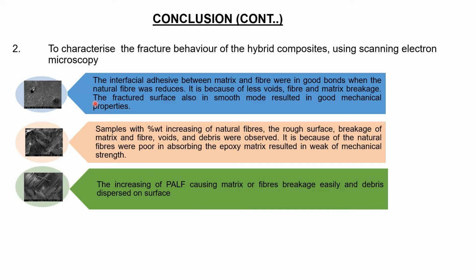Second objective, the interfacial adhesion between matrix and fiber was in good bond when the natural fiber was reduced. It is because of fewer voids and less fiber and matrix breakage. The fracture surface was also in smooth mode, resulting in good mechanical properties. In samples with increasing percentage of natural fiber, rough surface, breakage of matrix, and fiber void and debris were observed. It is because the natural fiber was poor in absorbing the epoxy matrix. And the last one, the increase of PALF caused the matrix and fiber to break easily and disperse on the surface.